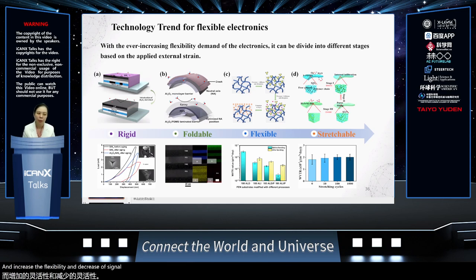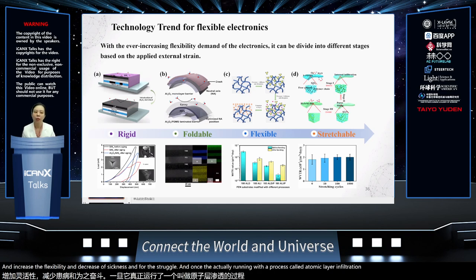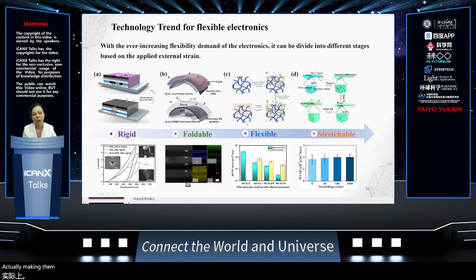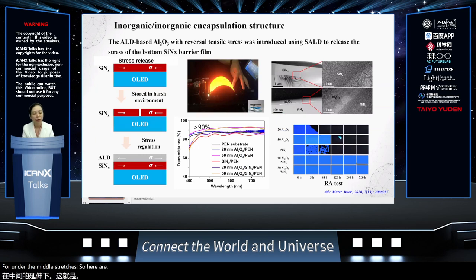We can run organic-inorganic nanolaminates to increase flexibility and decrease thickness. And for the stretchable ones, we run a process called atomic layer infiltration. Instead of making ceramic layers, we make more cross-linked materials that can survive a little bit of stretching. Here I'm showing a few examples that have been performed.